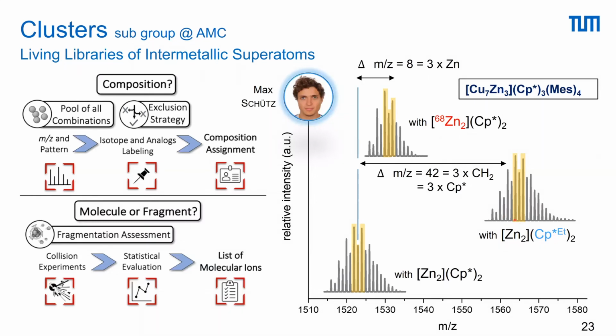And then you can also work out how many Cp star ligands are in this kind of multiplet. And by doing this multiple times, you can extract from your data, for example, that this species with high certainty would be Cu7Zn3 Cp star 3 mesityl 4. And by combining this kind of labeling, we can basically work ourselves through the dozens and dozens of peak envelopes which you create in such an experiment.